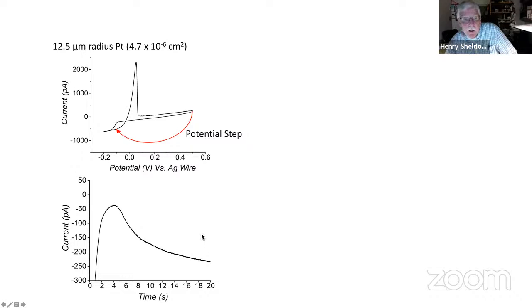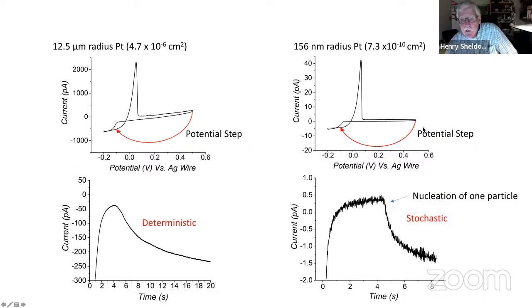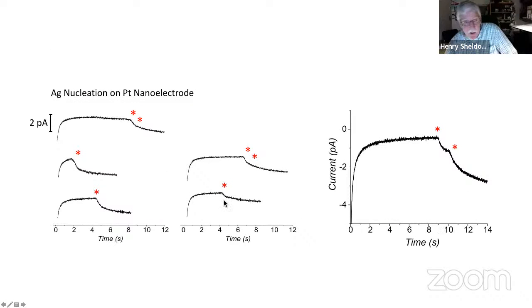All right, you do this at the nanoelectrode, same potential step. You see, here's the double layer charging, decreasing, and then there's no current, and then boom, you nucleate one particle. That's a stochastic process. And it's stochastic because if you do the experiment over and over, these are 5 traces for the same electrode, the nucleation event occurs at different times.